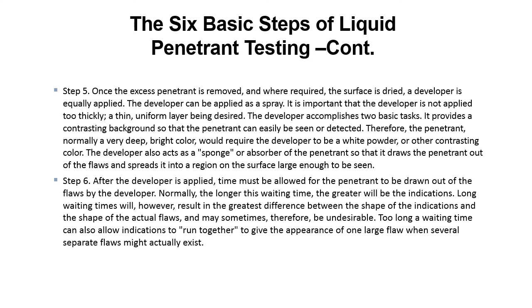Step six: after the developer is applied, time must be allowed for the penetrant to be drawn out of the flaws by the developer. Normally, the longer this waiting time, the greater will be the indications. Long waiting times will, however, result in the greatest difference between the shape of the indications and the shape of the actual flaws, and may sometimes therefore be undesirable. Too long a waiting time can also allow indications to run together to give the appearance of one large flaw when several separate flaws might actually exist.